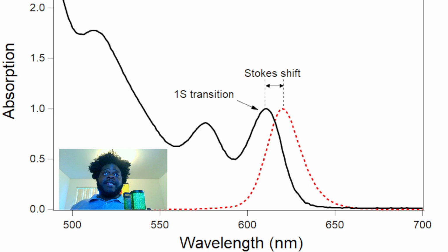And so the end result, at least in some materials, is that you'll get these really well defined peaks in the absorbance spectra. You can see here, this is the 1s transition. If you remember from chemistry, you have your 1s, 2s, 2p, and it goes on. Those are those electronic transitions in the quantum dot, and you can see them in the absorbance spectra.